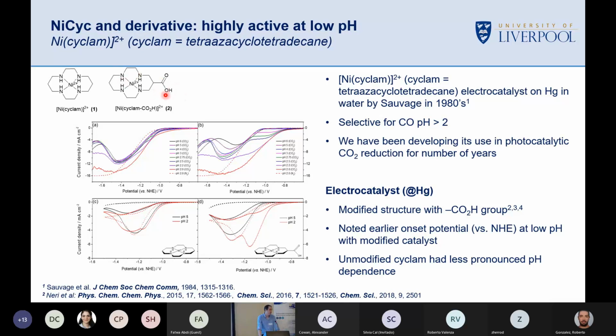This carboxy one doesn't really adhere too well in water, but what's interesting is it doesn't have this planar structure, of course. It's got a structure which we believe enables this carboxylate group to interact with the active site, either of its own one or of a neighbouring one. And when you protonate this carboxylate group at very low pH, we see a large acceleration in CO2 reduction kinetics, and that was a very nice observation. We could get very good selectivities.